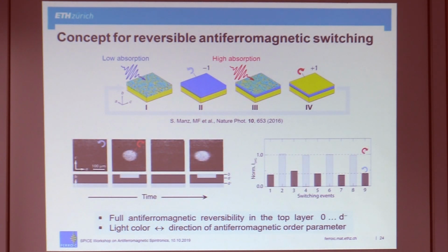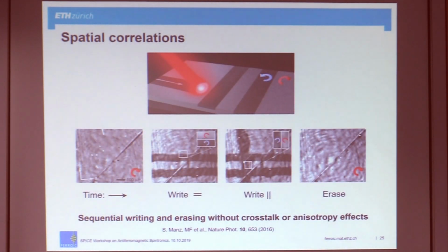So locally, we switch, flip back and forth our antiferromagnetic order parameter, and with it, the polarization, as many times as we want. It's not a bulk switching, but in this bulk region here, a certain thickness in our sample, we can do this as many times as we want. And we can also write with this.